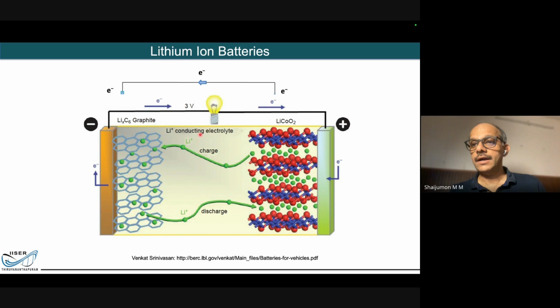It can be just a piece of paper. So it goes through it and lithium gets to this anode material, and this carbon combines with this Li+ and the electron coming through the external circuit to form a complex called LixC6, which means six carbon atoms get hold of one lithium to form this complex LiC6. When it is sufficiently charged, the entire lithium cannot and will not go to this place, because only around 0.5 lithium will go here. More than that, this structure collapses. So it is designed so that only that much lithium will go here, otherwise the structure will collapse.